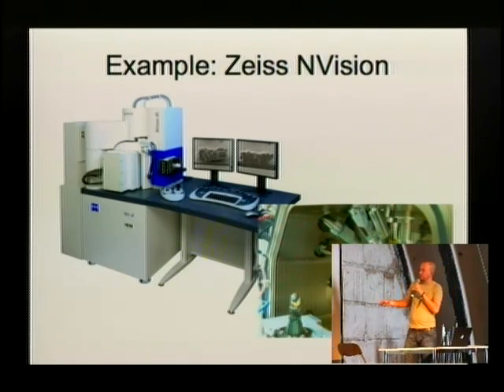Here is a close-up of the chamber of the microscope. Here in the middle you see the electron beam coming in. From this side, actually from behind, comes the ion beam, and you can mount your sample in a region where the ion beam and the electron beam cross. That gives you the possibility to use the ion beam to change the surface of the sample while you're watching the whole thing with the electron microscope.